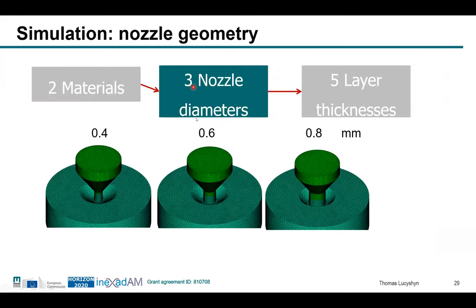We had a look at three different nozzle diameters. So basically this is the nozzle of the 3D printer. Here is the filament coming in, and here's the nozzle of the 3D printer. And we changed the nozzle diameter as a parameter to see the effect on especially the powder concentration, which was the main result we were interested in.